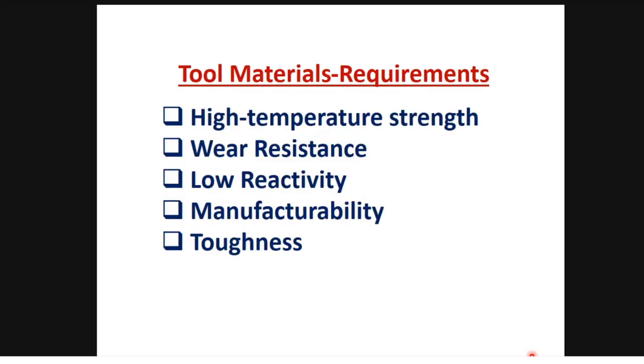You cannot use all materials as tool materials for joining high melting temperature material. If you want to use a tool material, it should possess these characteristics. One is high temperature strength, and the other is wear resistance. It should have very good wear resistance and low reactivity. It should not react at high temperature, and it should not react with the base metal. If you have all these characteristics, it's difficult to manufacture. Manufacturing is also very, very important, because you need to provide the sufficient pin diameter, the taper, and the shoulder diameter. All the profile you have to make in the tool. So manufacturability is very important. Then finally, it is toughness. So these are the requirements.